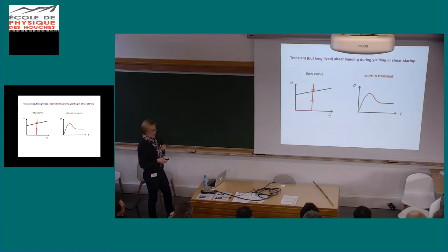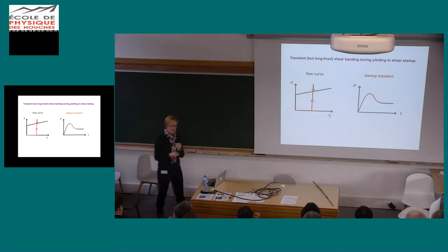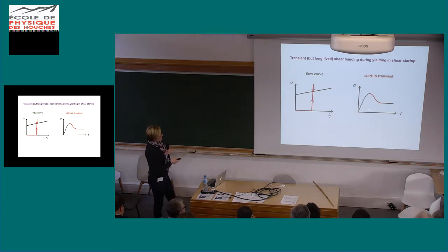So the most common way one does that is to start with an initially rested material, and then you suddenly jump the shear rate to some constant value, and you then hold that fixed for all subsequent time. So that's called a shear startup experiment. And you then track the stress as a function of the time since the inception of the flow, or equivalently of the accumulating strain.